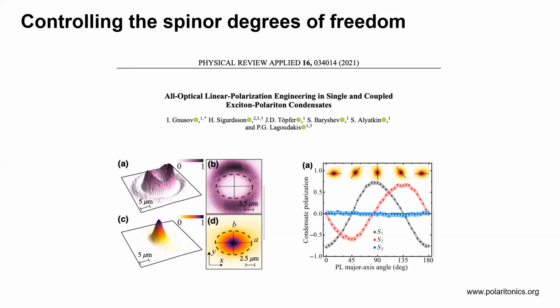So, of course, if you have a spin-up or a spin-down exciton reservoir, it will give you a spin-up or a spin-down polariton condensate. All right. So by measuring the polarization, now I can measure the spinor of the condensate. But if I have a condensate where there is no splitting between spin up and spin down, I can get a linearly polarized condensate. Okay?